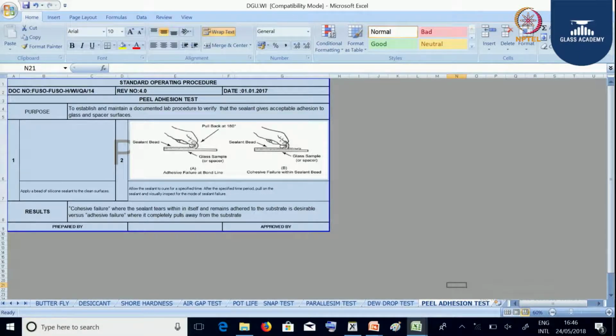Whereas in figure B you can see there is a cohesive failure, where some of the sealant is still sticking to the spacer. So with the help of this peel adhesion test, we can measure the adhesion between the spacer and the sealant.